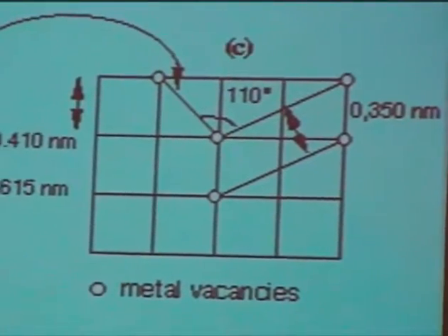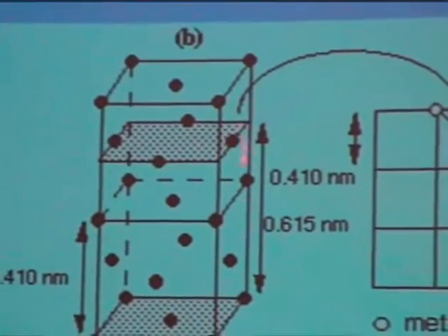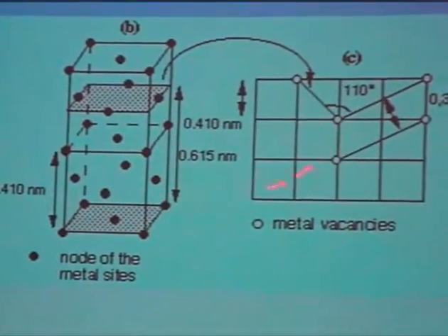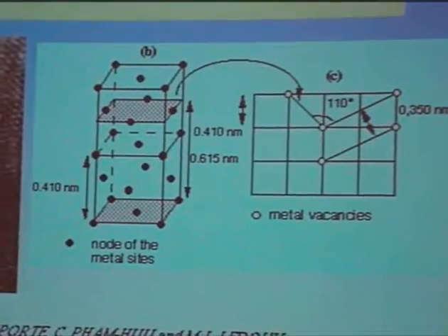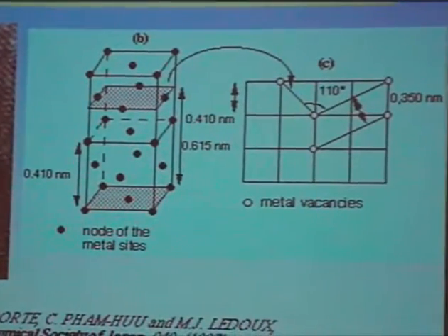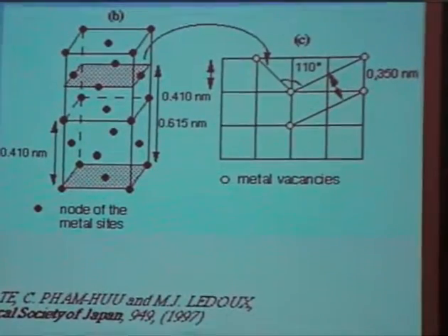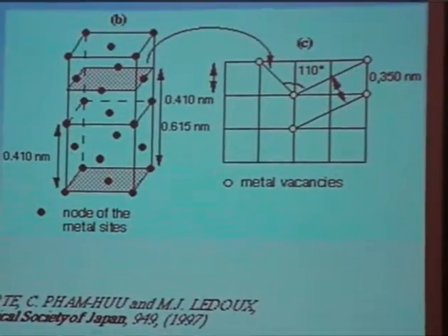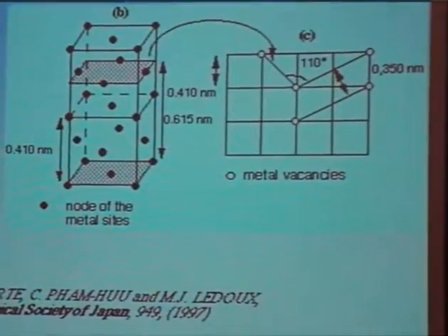explains this strange shape in chevron, but also you have the distance here, which is a new plane, which should not exist if you do not have these vacancies. And that explains why you have this band at 0.615. And I like this explanation very much, more than a reminiscence of the phase which would not have been transformed, which was my first explanation. But that was quite a tricky work to do, and thanks to Ted for doing that.